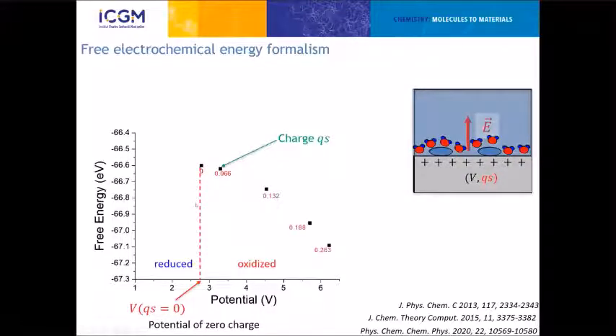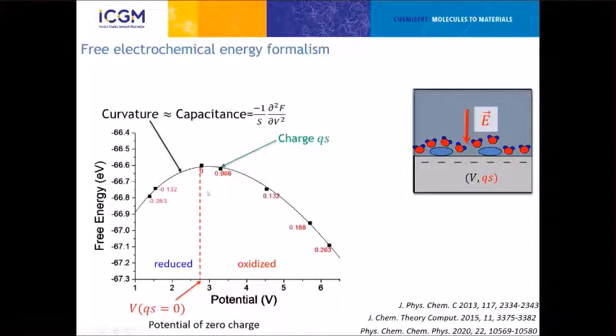We are going to charge the surface, and we are going to have more and more, for example, oxidized systems that will get different potentials that we are going to compute, and we can also get the reduced system. From this simple approach, we get the free electrochemical energy that is present there, and that is mostly an inverted parabola shape. At the bottom of it, you will get the potential of zero charge, and the curvature of it will be proportional to the surface capacitance. Then we already get some very specific features of surface and interface electrochemistry.